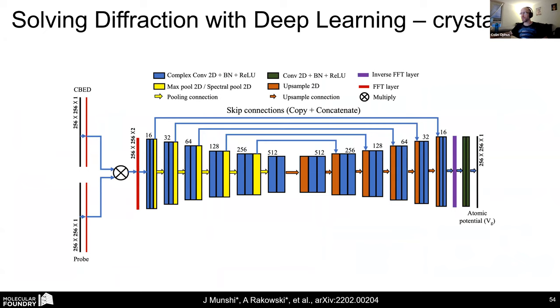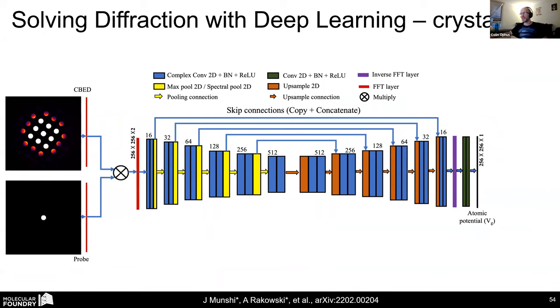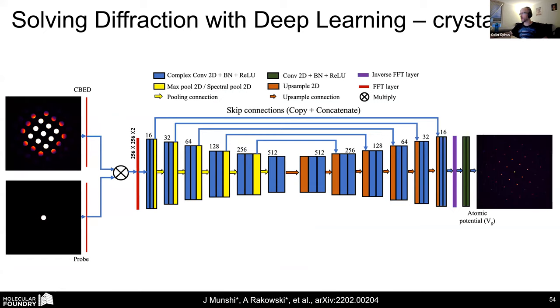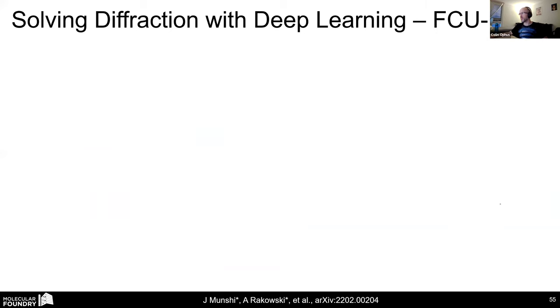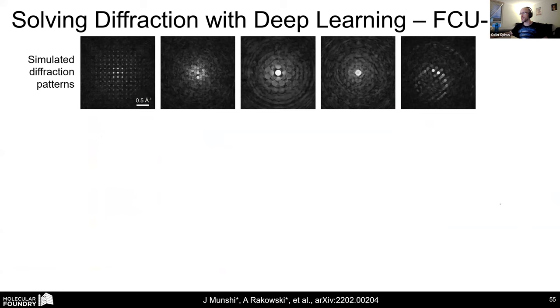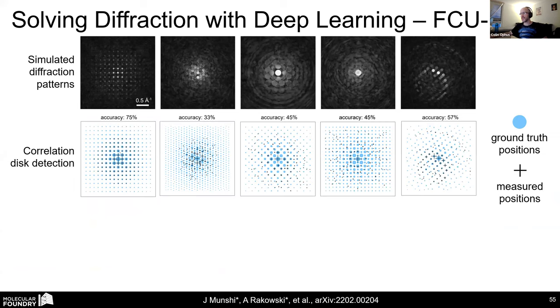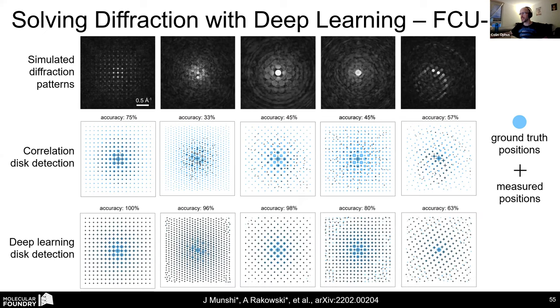Not that different from the U-Nets that you would find in the literature. It takes in the diffraction pattern of the probe, it operates in Fourier space with a complex activation layer and spits out these sort of atomic potentials or structure factor slices projected into 2D. And so if you apply this to simulated data sets here, comparing it to the conventional correlation disk detection, where the ground truth again is shown in these blue dots and the measured positions in the black crosses, it does such a better job. It's remarkably better.